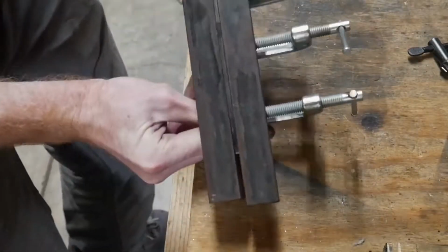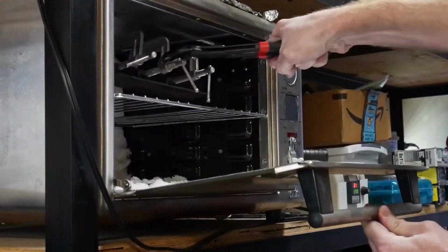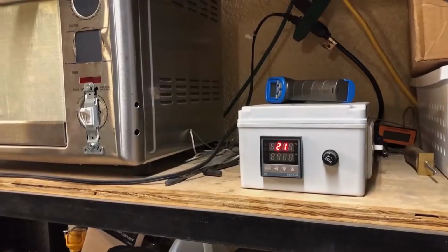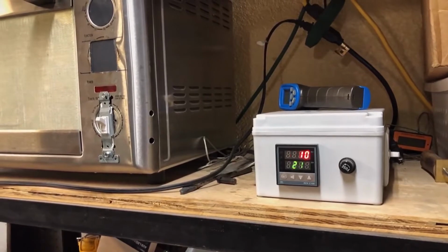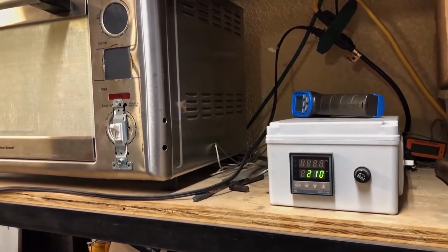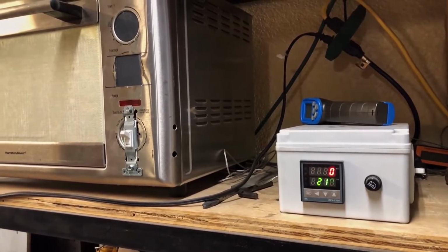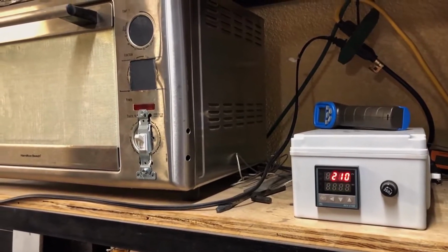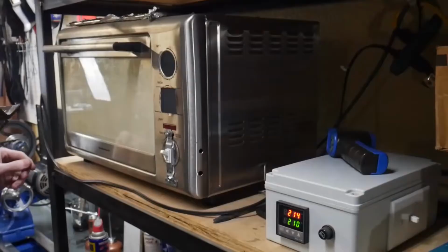This blade skated the file easily, so we will be clamping it between 2 pieces of angle iron to hold it straight and putting it into an oven for tempering. I will be tempering at 410 degrees Fahrenheit, which is 210 degrees Celsius, for 2 2-hour cycles. This can be done inside of a home range oven.